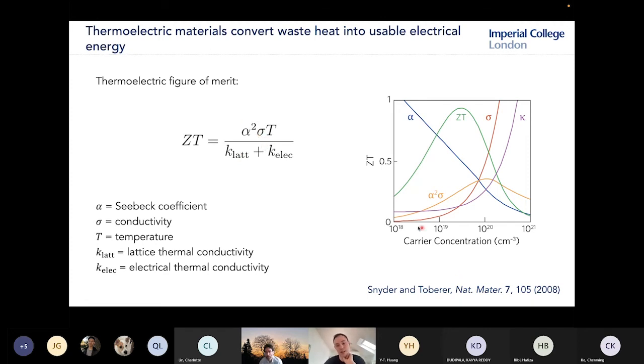So here I'm showing carrier concentration against ZT. And what you can see is that if we increase carrier concentration, we increase our conductivity, which is this red line, but at the same time, it reduces our Seebeck coefficient. And what we end up getting is quite a complicated behavior in the ZT with carrier concentration. And it's turned out that it's very difficult to predict computationally where the peak of this ZT is going to be and how high we can actually get it.